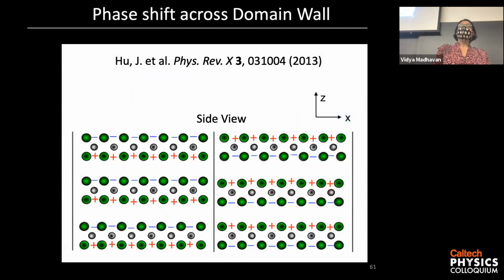And so interestingly, actually, this material gives you this as well. So there was a calculation in 2013 for these kinds of superconductors that I've been talking about today that showed that because of the nature of the material, the way you look at the hoppings in this material, you can show that the superconducting order parameter actually has a phase shift layer by layer. So this is the top tellurium layer. This has a negative phase, the bottom has a positive phase, and so on. So there's a layer by layer phase shift in the phase of the superconducting order parameter.